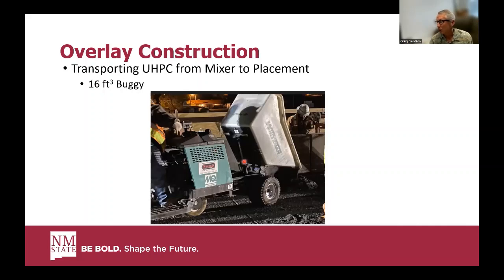So the mixers were set up at one end of the job site. Placement progressed from the far end back toward the mixers, and basically the 0.77 cubic yard batches would fill 2 of these 16 cubic foot buggies, and the buggies just transported the UHPC to right in front of the screed, put it down on the ground, and then it was shovel work, some hose, and then vibration to spread the UHPC out in front of the vibrating screed.